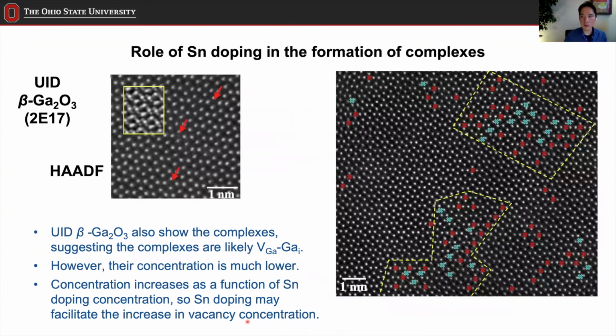To confirm the hypothesis, what we need to do is look at another sample that has lower doping concentration. As I said, the sample that I already showed you is the one that is heavily tin doped, with a carrier concentration near 10 to the 19th. So what if we look at the sample that is not doped? This was doped, but this is not doped. But the gallium oxide substrates tend to be already doped naturally, so even if you don't intentionally dope the sample, it has a carrier concentration of about 10 to the 17th. That's why we call this unintentionally doped. But one thing for sure is this one does not have tin, because you get tin only if you intentionally put it in. So at least we know that there's no tin here.